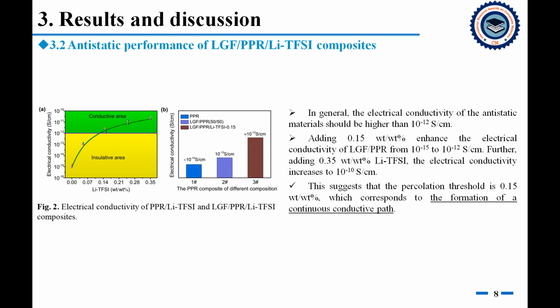3.2 Antistatic performances. We further explored the antistatic properties of the fiber-reinforced system. We found that adding 0.15 weight% reduced the electrical resistivity of the composites to the lowest value of the antistatic materials. This suggests that the percolation threshold is 0.15 weight%, which corresponds to the formation of a continuous conductive path.